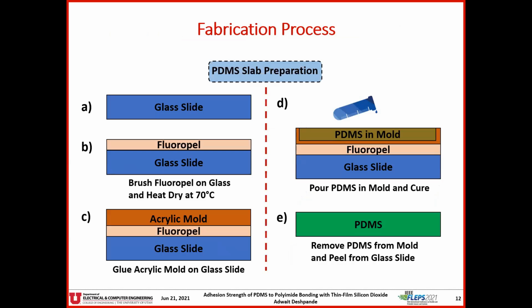Moving on to the fabrication process. For preparing the PDMS slab, a microscope glass slide was first coated with fluoropyl to facilitate easy release of PDMS. An acrylic mold was then glued on to the coated glass slide. Sylgard 184 PDMS was mixed in the ratio of 10 to 1, degassed, and then poured in the mold. PDMS was cured at 120 degrees Celsius for 1 hour and then peeled off from the mold.